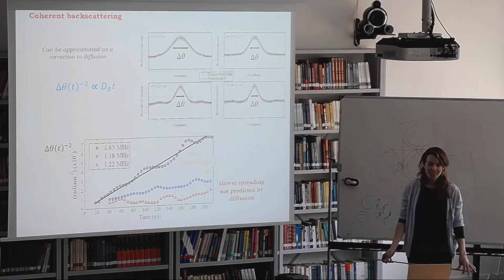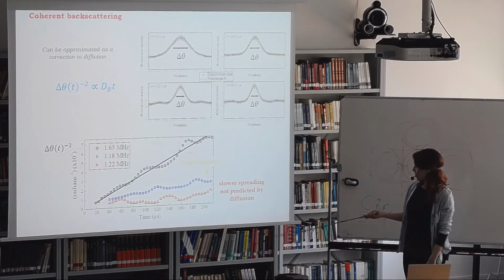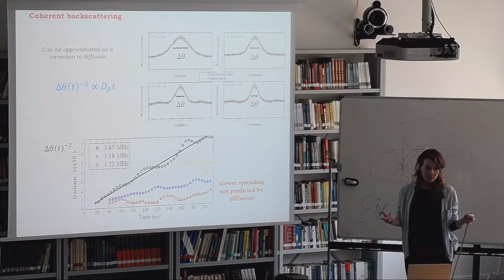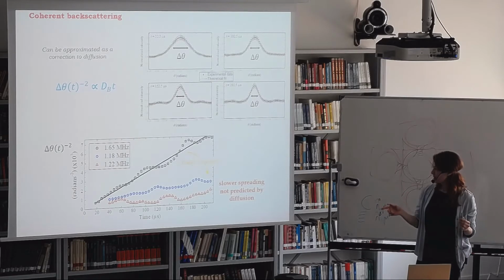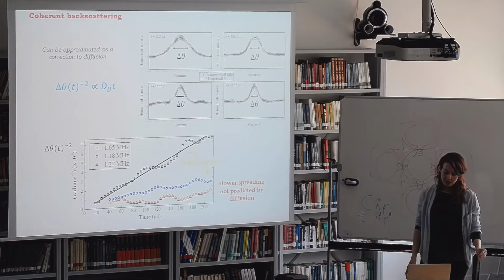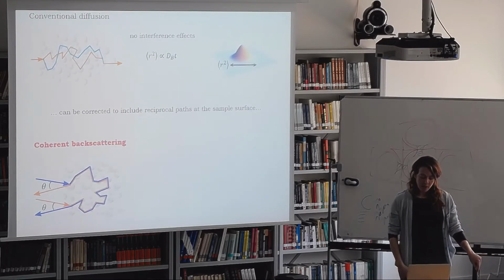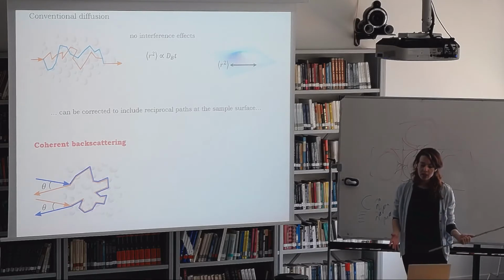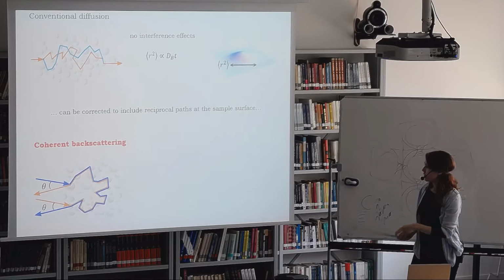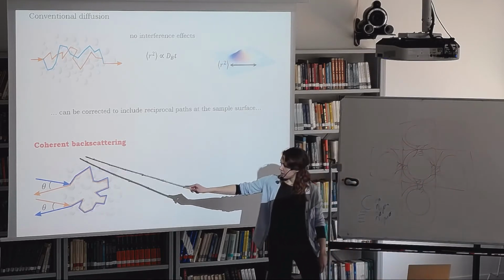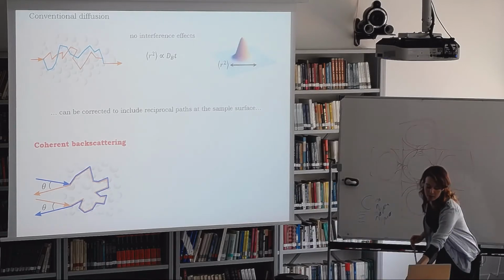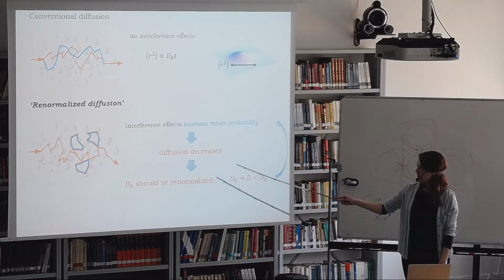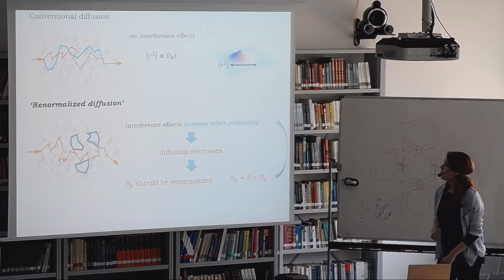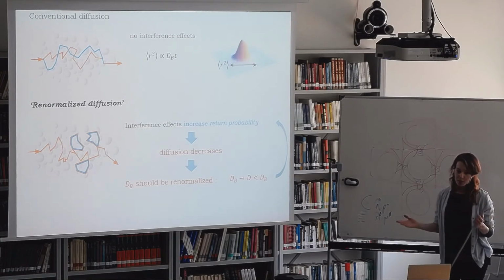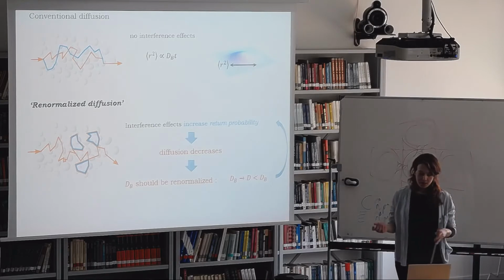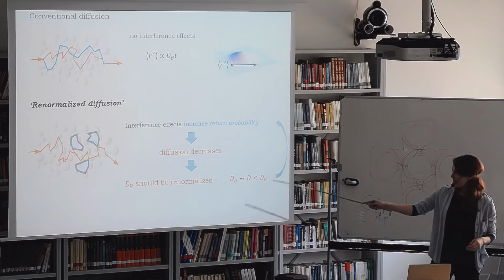However, at different frequencies, we see measurements which do not agree with our theoretical prediction. So even though we've calculated a correction to diffusion to account for these different reciprocal paths, we still can't describe the behavior at all frequencies. So this means that the explanation for this is that we haven't taken into account enough of the reciprocal paths. What we've done is made a correction for the reciprocal paths which have their beginning and end at the surface of the sample that we're measuring. But in fact, they can occur inside the sample as well. And so if we want to completely describe the propagation in this regime, we need to account for all the interference effects due to all these kind of reciprocal paths inside the sample.